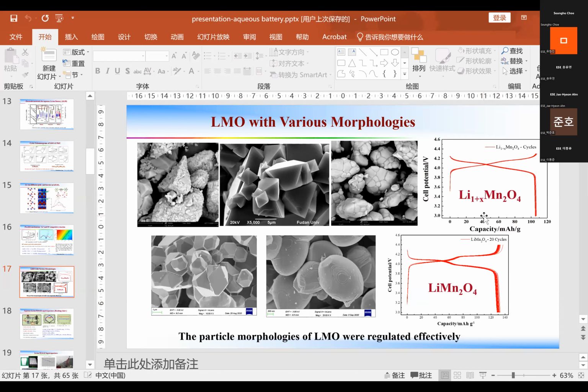If you go to cycling stability, we use a lithium-rich one, and for the high capacity, we use this one. But the cycling stability also depends on the surface area. Very recently, we use this type of one. We can get a good cycling stability in aqueous systems.